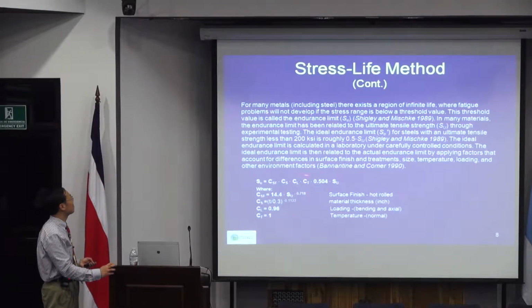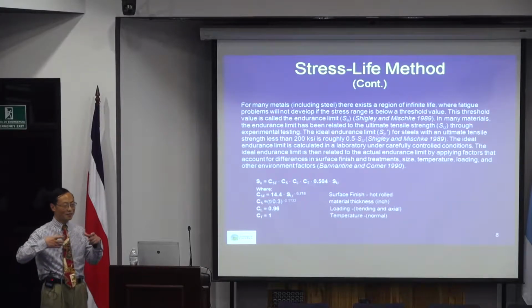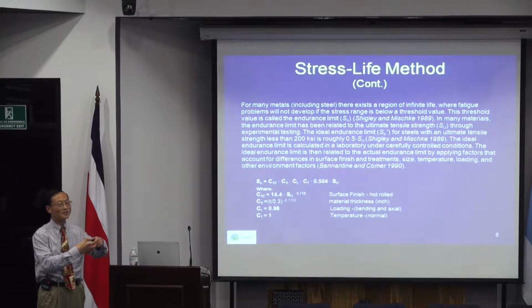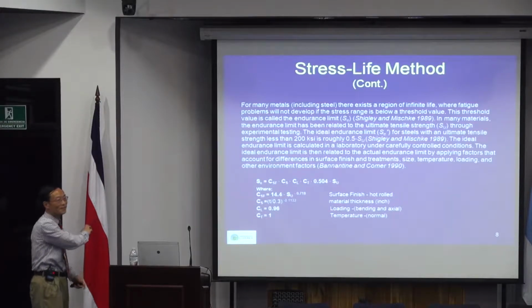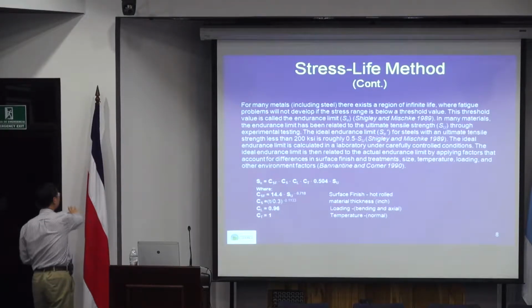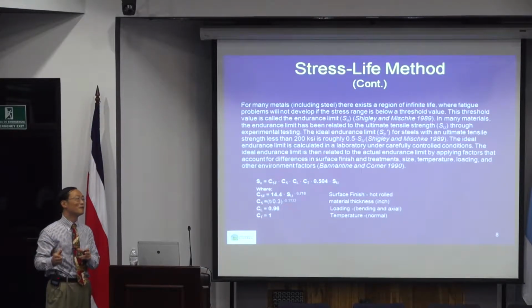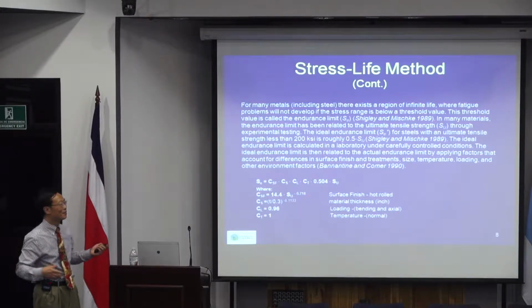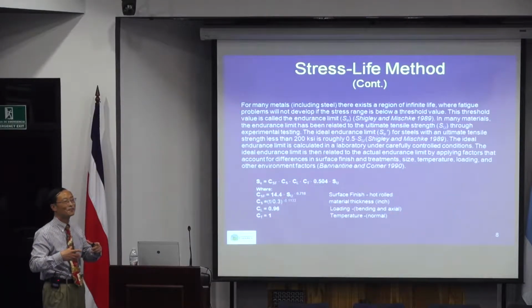Also, usually the fatigue capacity is modified, just like concrete. When you do the concrete test, if you have a very small cylinder, you get a little bit larger capacity than a bigger cylinder. The reason is that when you have a bigger cylinder, the probability of defect inside is much larger than a smaller cylinder. That's why you have a standard cylinder test. But sometimes, if you want to take samples from an existing bridge, you don't want a bigger core. You have a smaller core, and your test is higher, so you have to apply a modification factor to lower that to a standard. It's the same with larger size members: they are more likely to fail than smaller size.